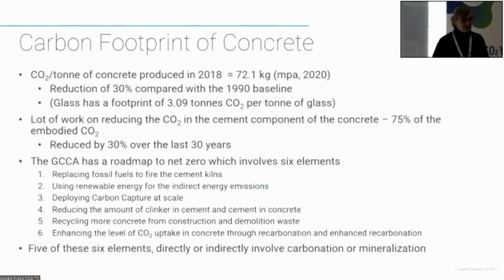So the carbon footprint of concrete, I think in about 2018, the MPA published a figure that 1 ton of concrete produced 72.1 kilograms of CO2. But they were very proud to announce that that was a reduction of about 30% on the 1990 figures. Just for comparison, glass has a footprint of 3 tons of CO2 per ton of glass. I'm not going to talk about how we can do anything about the glass industry. It's a real challenge because it's a thermal process.